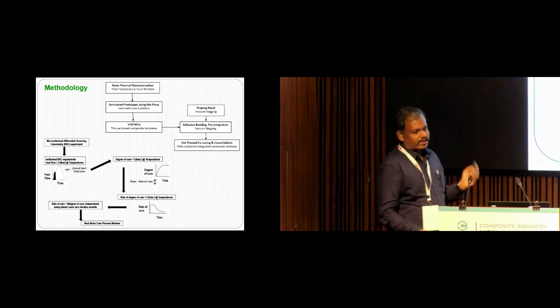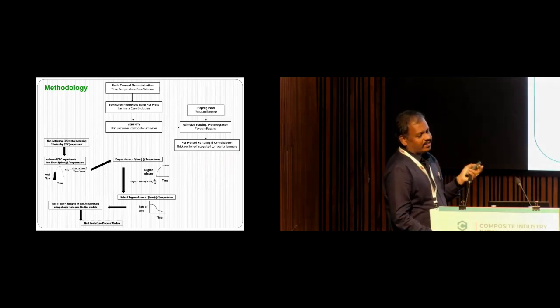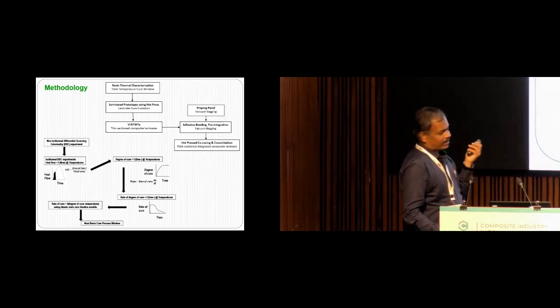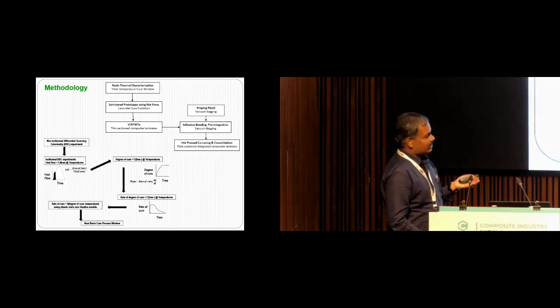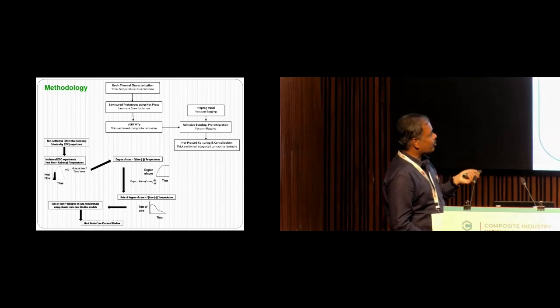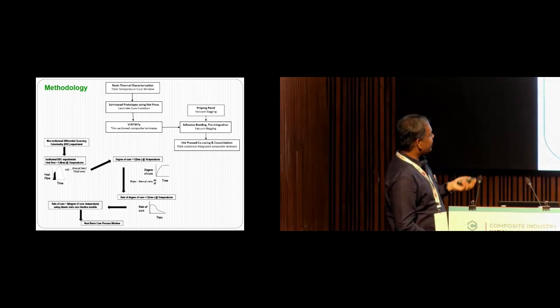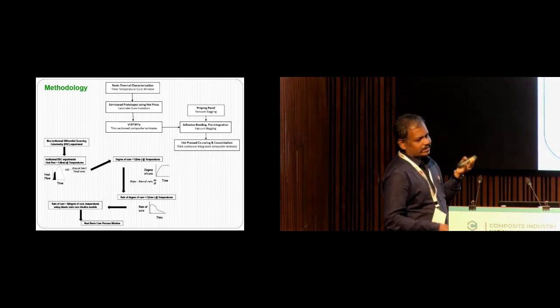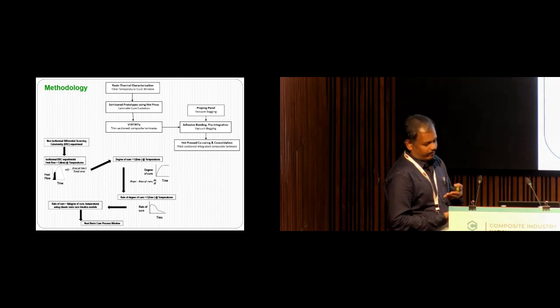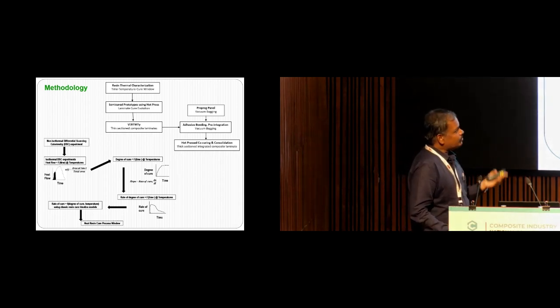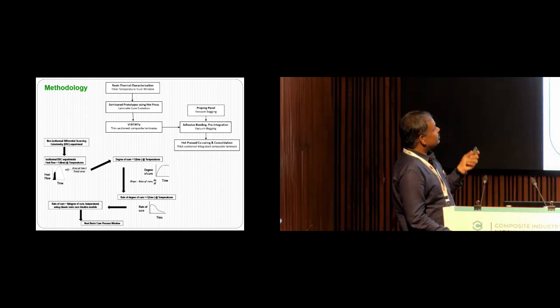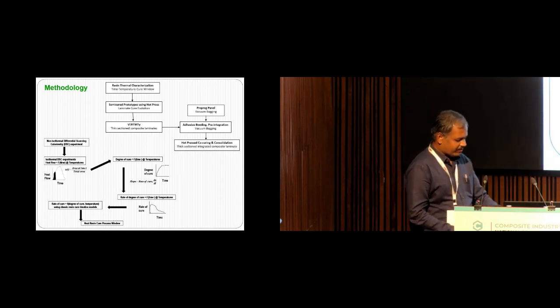Okay, so this is the total methodology. To prepare the semi-cured composite laminates, first of all you have to do the thermal characterization of the resin through differential scanning calorimetry. From that you should obtain the time-temperature cure window for the resin. Then you have to develop the semi-cured composite prototypes through different molding techniques, and with the use of thin film adhesives you have to co-cure and make the one-shot thick section composite laminate. I will be dealing with the thermal characterization of the resin in the later part.